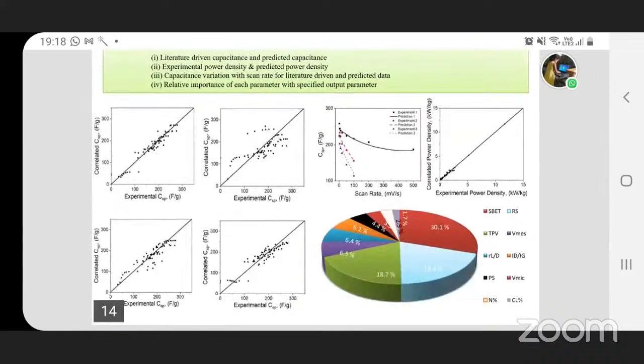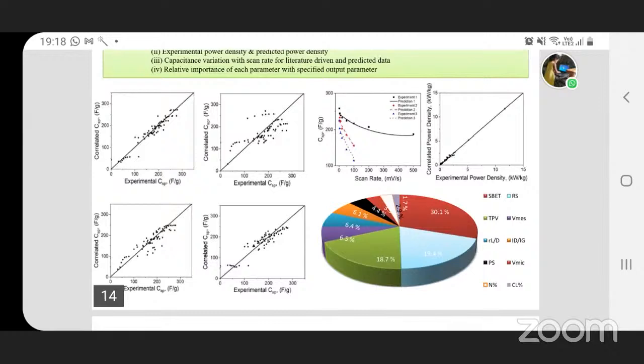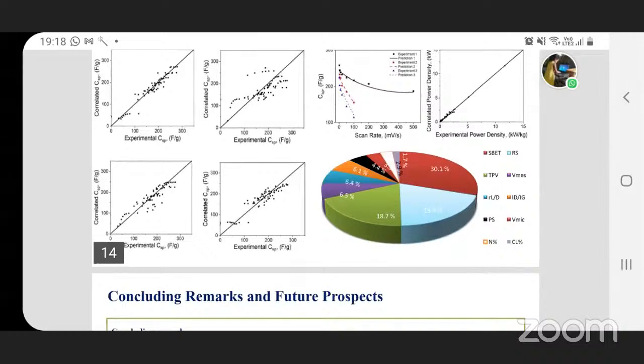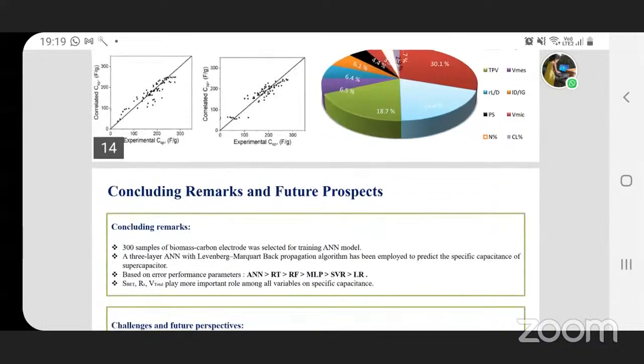After that, we went for the scan rate evaluation or variation along with the specific capacitances. We found that it was in very good agreement with the specific capacitances, and we further moved to the experimental power density with the variation of the nitrogen content. For example, we considered the different percentages of nitrogen which are used in the literature, and then we found, as is evident from the pie chart, the different parameters show different contributions to the overall specific capacitance value. Three parameters are having the major role, that is the total surface area, the internal resistance, and the total pore volume, whereas in comparison to these three, nitrogen percentage was having a less significant role.